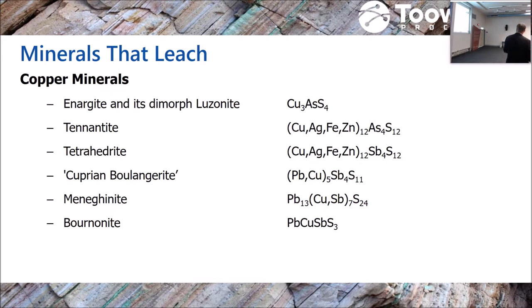So what's happening in the leaching system is the arsenic atoms are bonded to sulfur atoms, and our caustic-based system has sulfide ions in it. For some reason, the sulfide ions in the solution have a greater affinity for the arsenic or antimony atom bond. It's bonded to two atoms in the mineral lattice, and it says, well, I'm happy to let go of these bonds and jump onto that bond in the solution. So from a mineralogical and mineral lattice point of view, we can actually understand what's happening to different minerals.